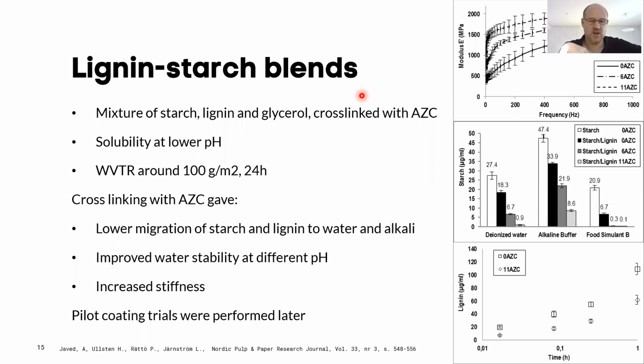We had something that resembles a water barrier, 100 grams per square meter, 24 hours. It's not a good water barrier, but it's at least stopping some water here. So as a first trial, you can see it as okay. What happened when we actually looked at starch and lignin and took the cross-link, we actually increased the stiffness of the materials, as you can see in the DMA measurements here, with 0, 6, and 11 parts of AZC.